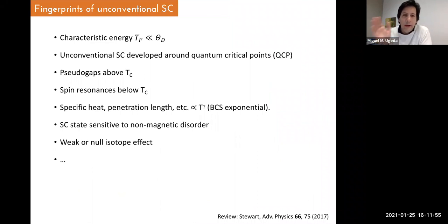There is a long list of fingerprints that we can study in order to learn if a superconductor is unconventional. I'm not going to get into details here. Let me just briefly mention some that can, in general, be probed with the STM. For example, the existence of pseudogaps, the existence, I will show you in a second, of spin resonances below the critical temperature, or, for example, the sensitivity of the superconducting state to non-magnetic disorder. In general, conventional superconductors are not sensitive to non-magnetic disorder up to a certain level, but this doesn't apply to unconventional superconductors.